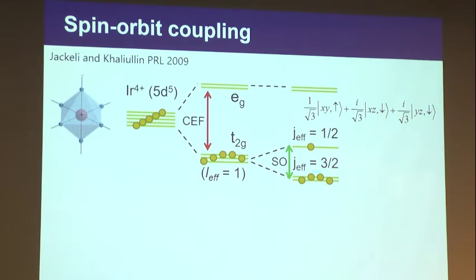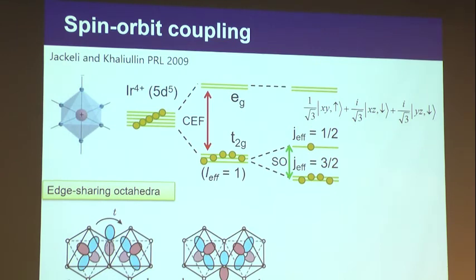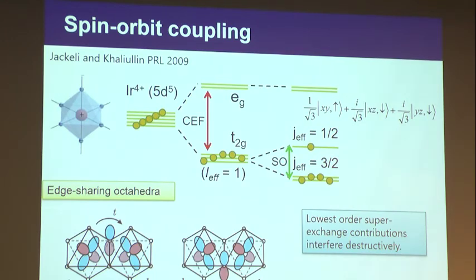If the spin-orbit coupling is not strong enough, then you are not going to achieve this. But what's more interesting is if we put these two things together and investigate the magnetic interaction between these two effective J = 1/2 moments, then the dominant contribution that you initially think about is the superexchange interaction through the intervening oxygen lying over here. You think about hopping from here to here and hopping from here to there. The important thing is there are two paths. And it turns out that in this type of strongly spin-orbit coupled system, these two paths interfere destructively and basically cancel each other. That means you have to go to the next highest level of perturbation theory. They found that if you do that, it actually gives you the Kitaev interaction, and the reason is that this has a strong spin-orbit coupling with the 3 orbital states mixed in.